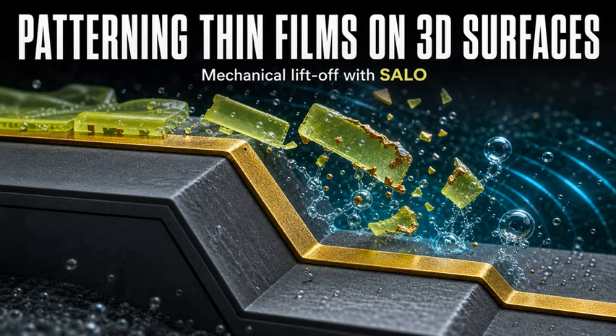Well, to get to those dream applications you just mentioned, we first had to tackle the notorious conformal coating problem, especially with ALD, atomic layer deposition. Because ALD is almost too good at its job, right? Exactly. It coats every single microscopic crevice perfectly evenly. But that perfection is an absolute nightmare for traditional solvent-based lift-off processes. Yeah. The conformal coating just completely seals in your sacrificial resist. Oh, so the solvent literally can't reach the sidewalls to dissolve it. Right, the resist is just trapped in a shell.